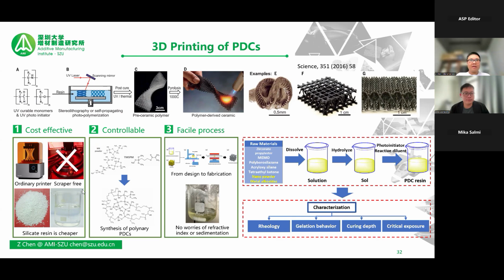And the resin, of course, is cheap, and one more thing is we can have very fine control over the molecular level. Then we can dope lots of materials, like titanium, zirconium, ferrite. So all sorts of materials we can dump inside at this molecular level. The doping or controllable recipe can be very advantageous, because enhanced performance, like mechanical properties and also electromagnetic performance, can be enhanced by this kind of strategy.